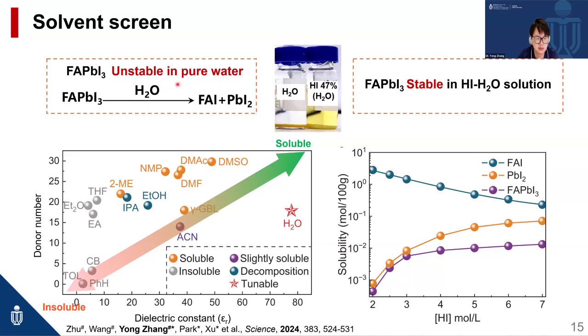FAI could dissolve, but lead iodide has limited solubility, making it precipitate. But we found that FAPbI3 could remain stable in hydrogen iodide water solution with a clear solution, and the precipitate color does not change.